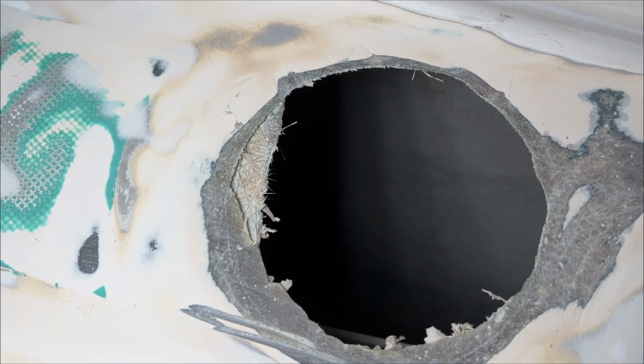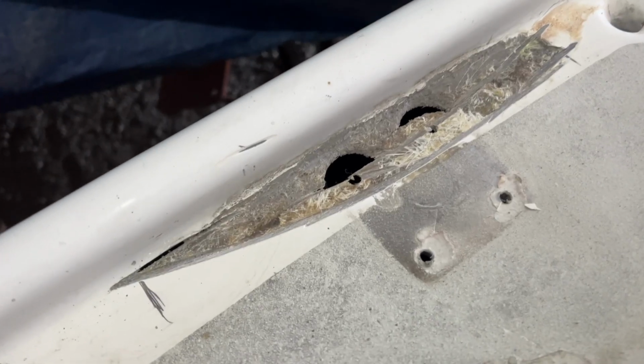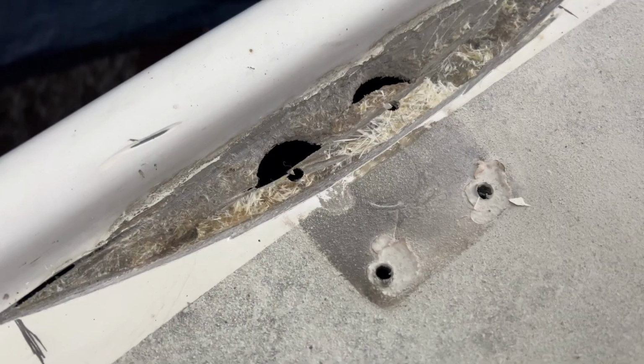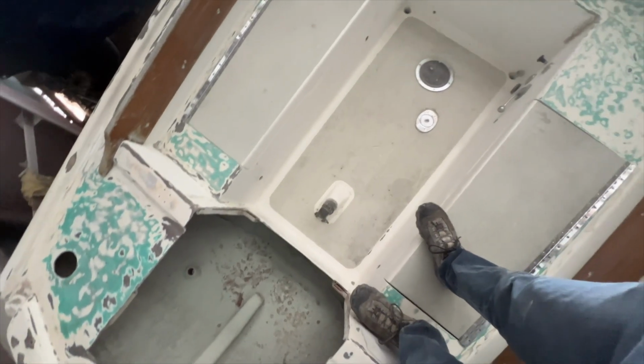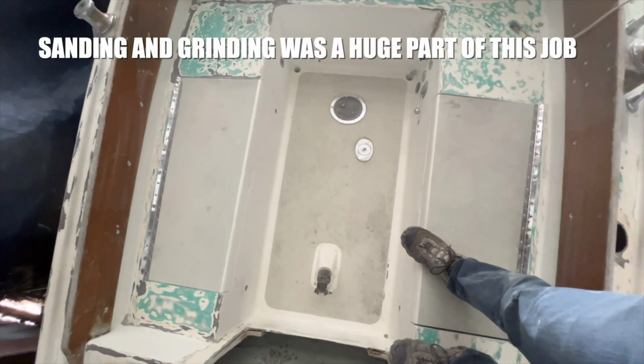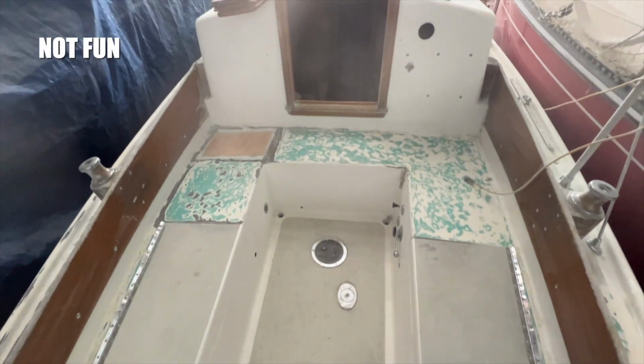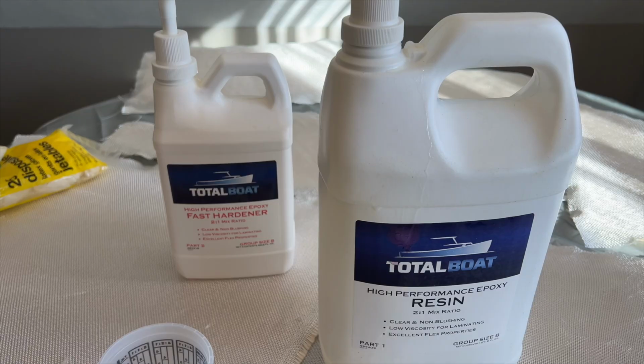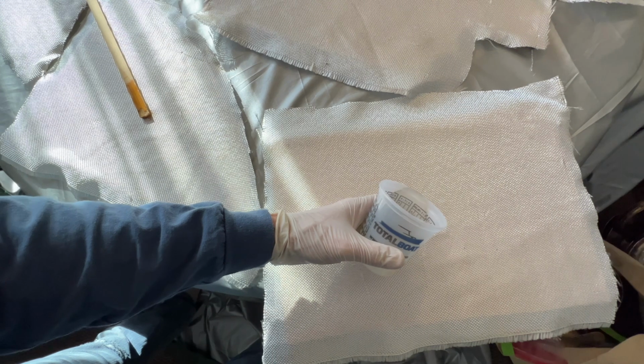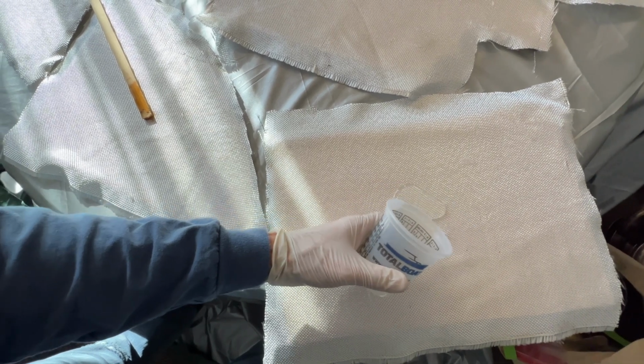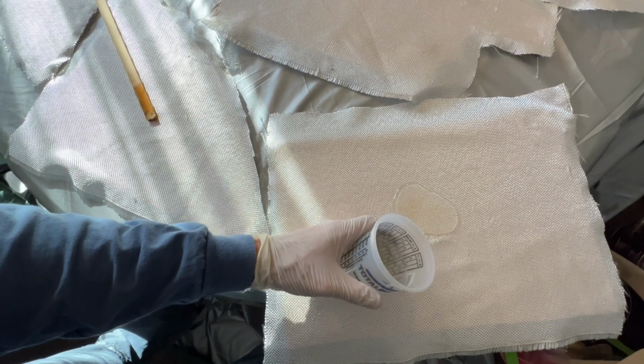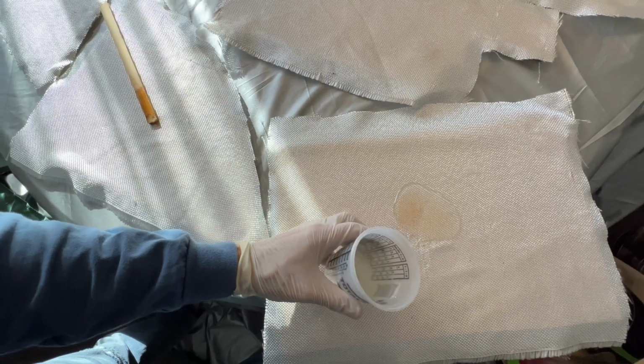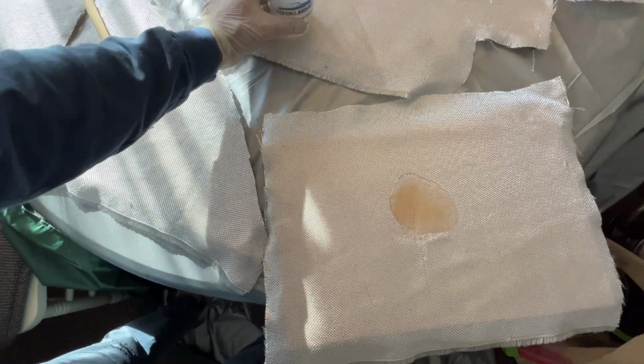I had a few other problem areas in the deck surface. I had the hole where the gas intake once was. I also had some cracks and damage around one of the stanchion posts. There were in fact a lot of little cracks in the surface, so I sanded it all down and prepared to do some repair work. Once again, I turned to Total Boat's fast hardening epoxy resin and applied 1 layer of 10-ounce fiberglass and epoxied it down to the piece of plywood that would cover the icebox opening.